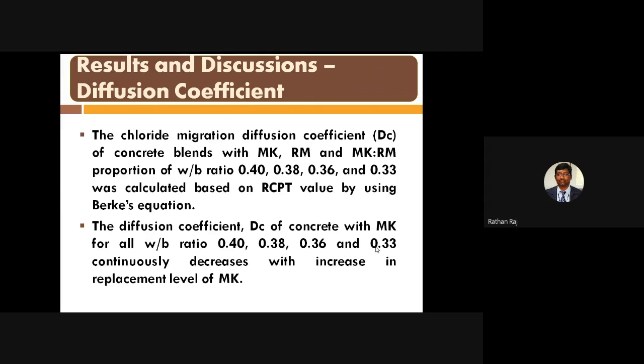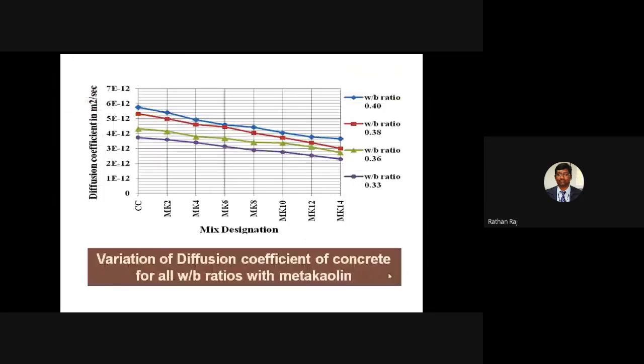After that, it is applied in Berke's equation, and the diffusion coefficient was calculated. So there are some notable values. This graph shows that for the metakaolin replacement, starting from 2% up to 14%, in all the replacement levels, the diffusion coefficient is decreasing.